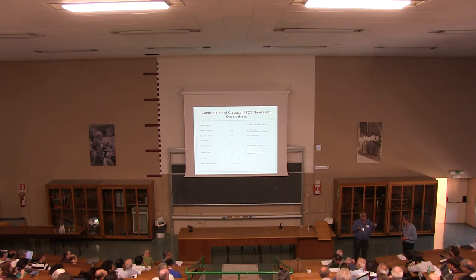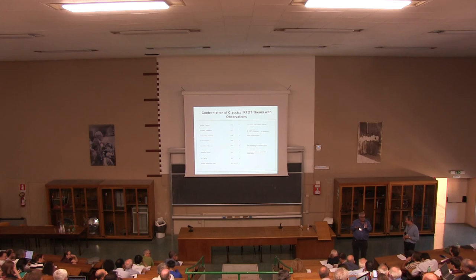And by the way, that has a prediction about something you can observe. That's never been observed because you have to go to a very low entropy to see that. But what it says is that if you already have a surface that's crystalline, there's a regime, the normal regime, where the rate of progression of the crystal front depends on the diffusion coefficient in the material and is very low. But you cool lower, and when you cool lower, you get to the point where it's easier to directly nucleate on the surface, and now you get a much faster crystal growth. So that's actually been observed and is one of the consequences of the theory.